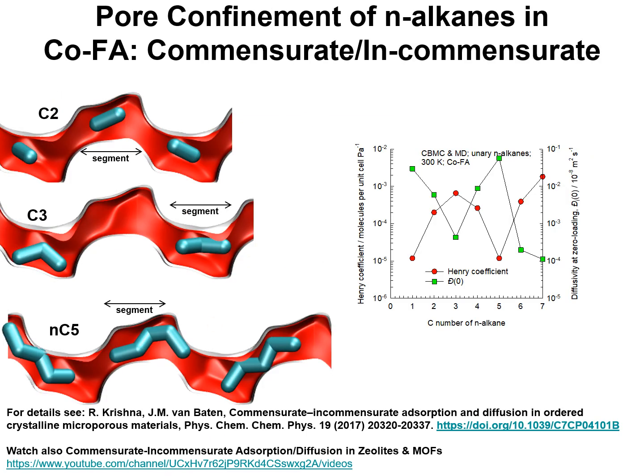Let's examine the diffusivities of normal alkanes in cobalt formate that consists of zigzag channels that are one-dimensional. This is the length of one segment. This is the second segment. A propane molecule has a length that is commensurate with the segment lengths, and it sits comfortably.